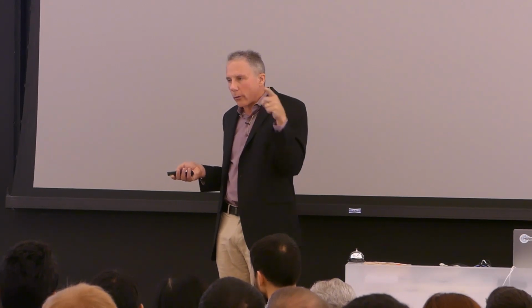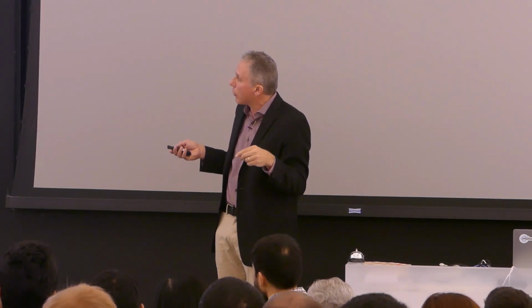They have very high radiative efficiency, and the sort of physics that I told you about of photon trapping and recycling is also operative in these luminescent solar concentrators, just like it is in the high efficiency direct bandgap solar cells. And in this case, we use also light trapping mirrors to trap luminescence radiation. And so then light is effectively absorbed in the vicinity of a small solar cell and captured and concentrated onto a small solar cell from a larger capture zone. And that geometric gain, which is the absorption area over the collecting solar cell area, defines the concentration factor in the limit that all those photons are collected.